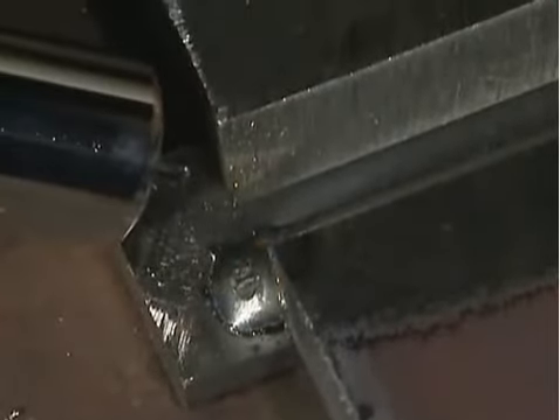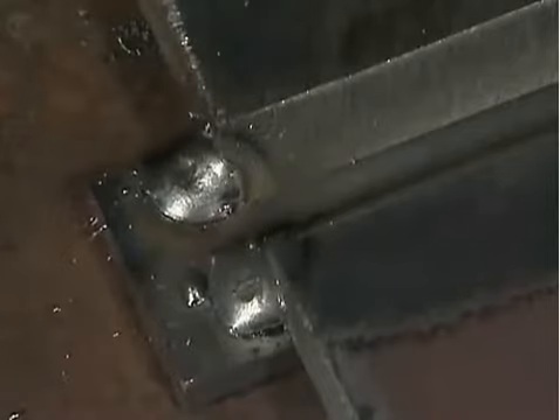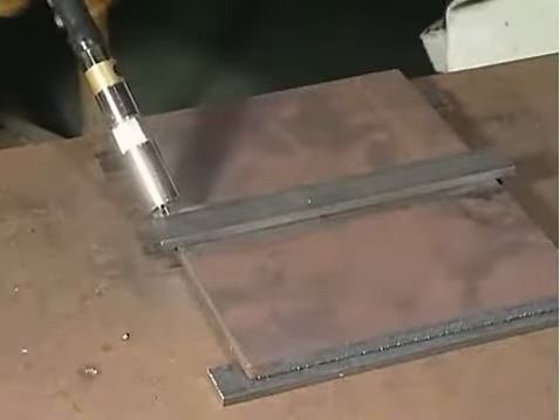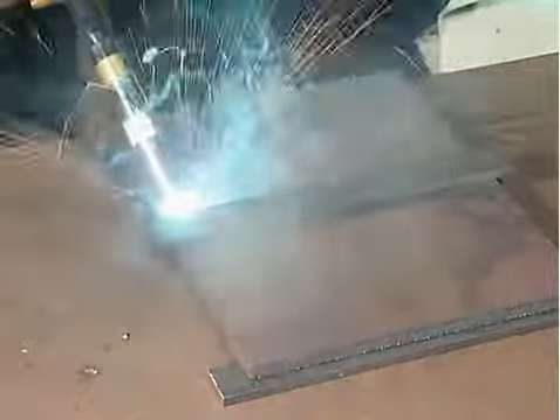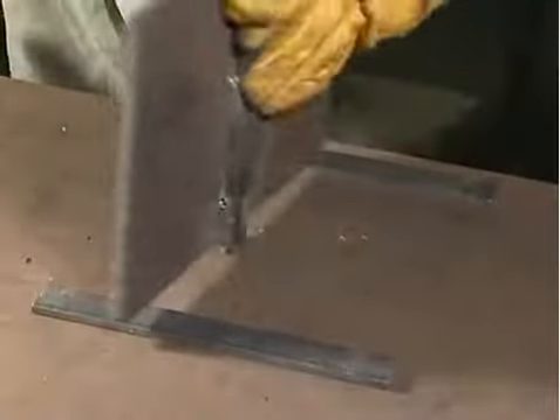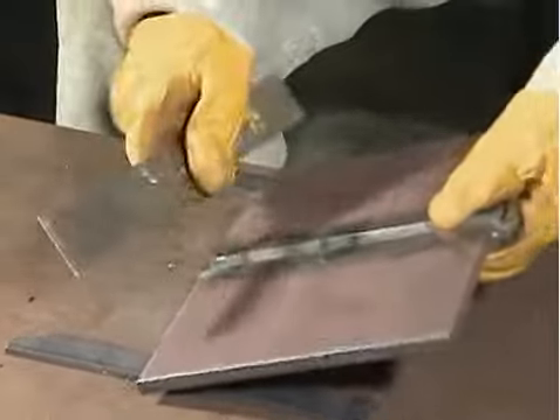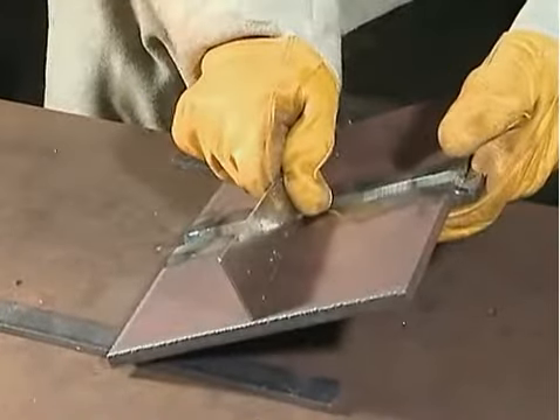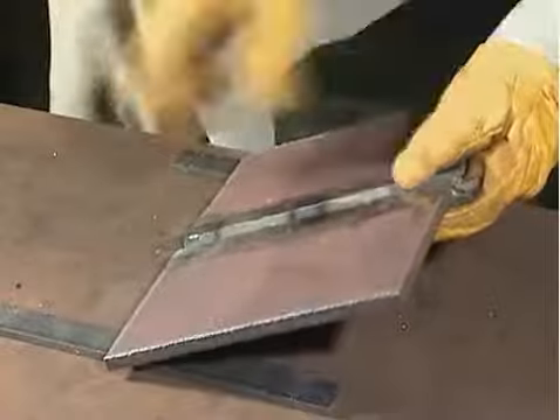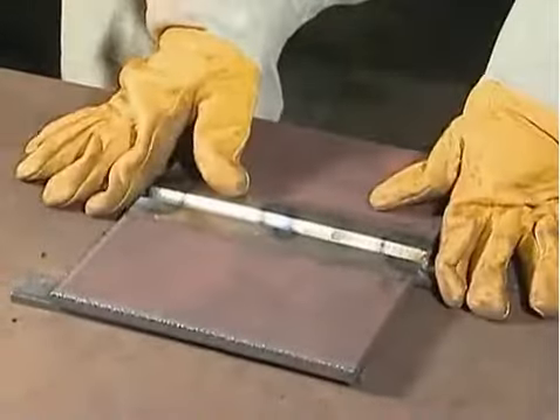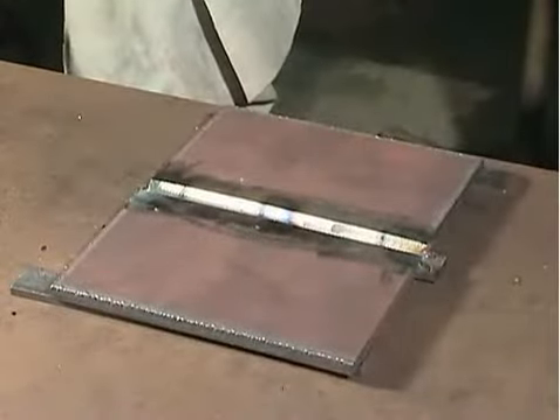The root opening should be 4 to 5 millimeters. Make sure that there is no gap between the workpiece and the backing metal, that the root opening is within the prescribed dimensions, and that there is no significant difference between the two ends. After the tack welding, use a reverse strain gauge and make a preset distortion of about 3 degrees. This will counteract any distortion in the workpiece after the welding is finished.